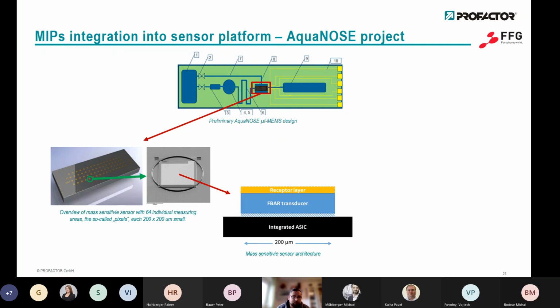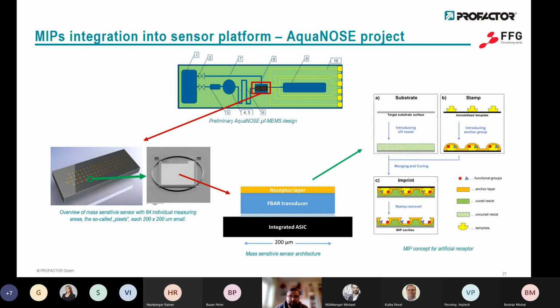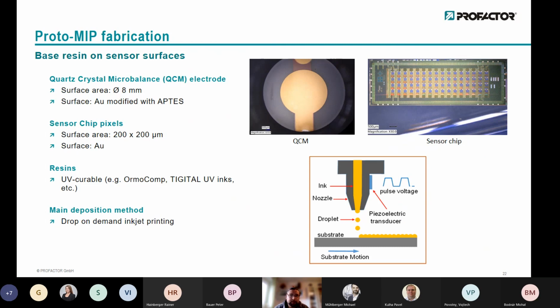So basically, what you do is measure the frequency, like on a QCM. It's not selective, but it's sensitive, and therefore you need to introduce a receptor in the end, and this is basically then the MIP. So in a lithographic method, this is deposited onto this chip. So we played around with different things. The main target again was inkjet printing.